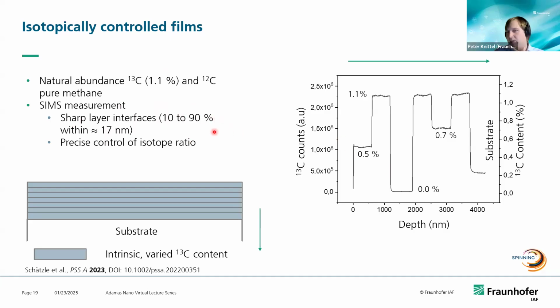And into these layers, if you require single NV centers, you can also go ahead and do implantation again, or try to produce them by growth in this layer. So we are able to achieve here very, very nice, sharp interface layers with our system, and thicknesses down to tens of nanometers actually. So this is a bit larger here for actually measurement purposes, but the lowest we can go at the moment is in the range of 10 nanometers for an intrinsic layer.